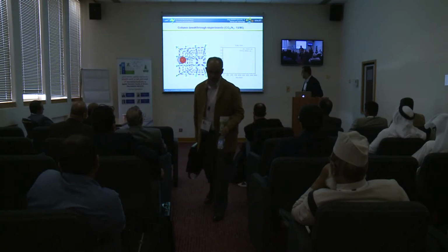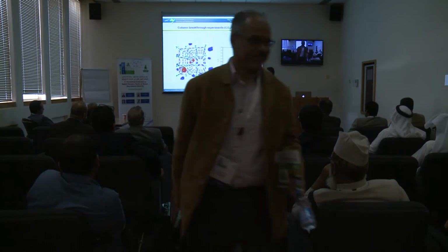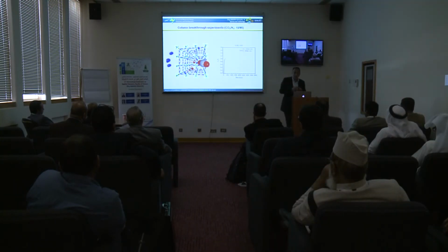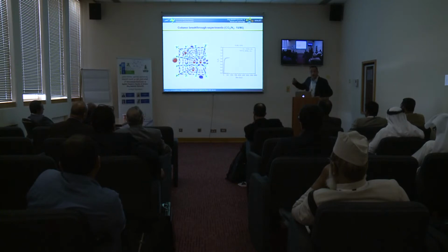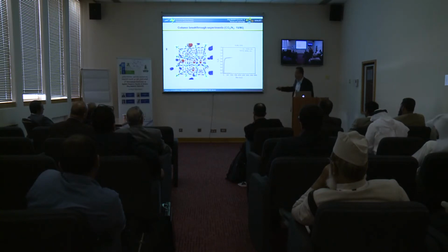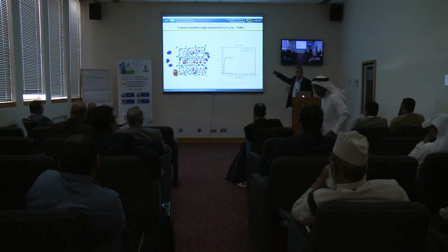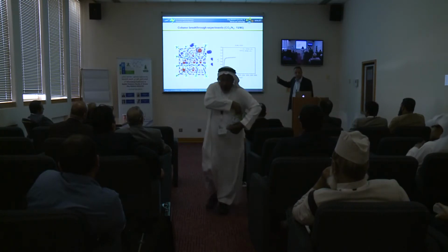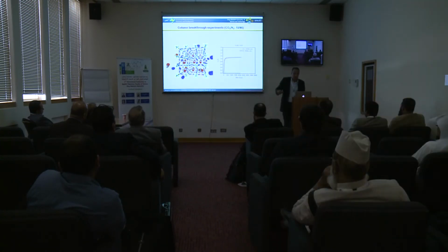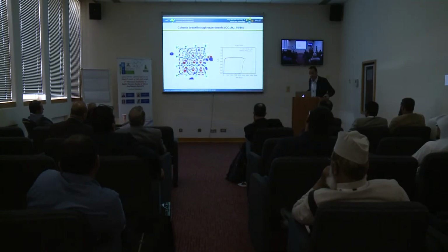Here you can see what you have is a periodic array of fluorine anions sitting in a square that allows CO2 to interact with 4 centers, and you have kind of a spillover, where the first CO2 that adsorbs goes to the next one and the next one behind. Then it allows, for the first time, what we call thermodynamics and kinetic driven adsorption that allows this material to be highly selective. So we are trying to scale up this material, and it should be a good material to use for separation.